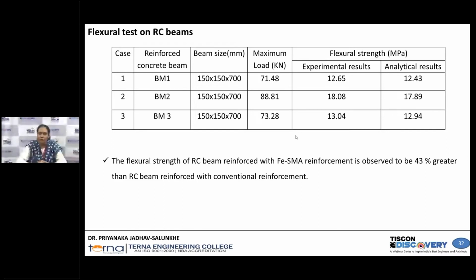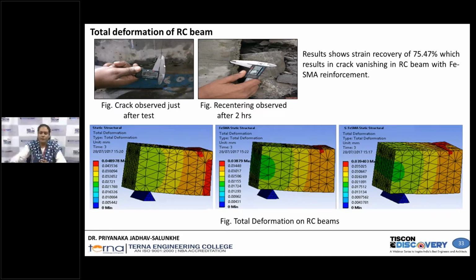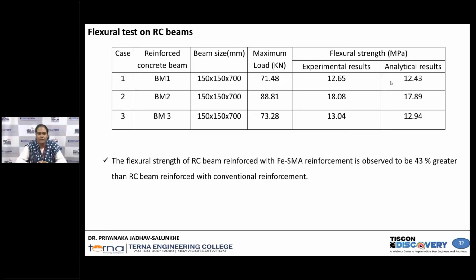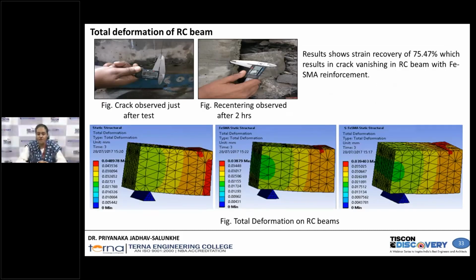Now, the main phenomenon of the shape memory alloy, or what is the effect of shape memory alloy? See, in these two figures, the first is the beam cracks observed just after the testing, and the second figure shows the recentering ability of the Fe-SMA reinforcement after 2 hours of the testing. The result shows that 75% of the crack vanished after 2 hours of the testing. So this is the benefit of using the shape memory alloy in the structure. 75% of the strain recovered in that structure, and the same results we compared in ANSYS also.